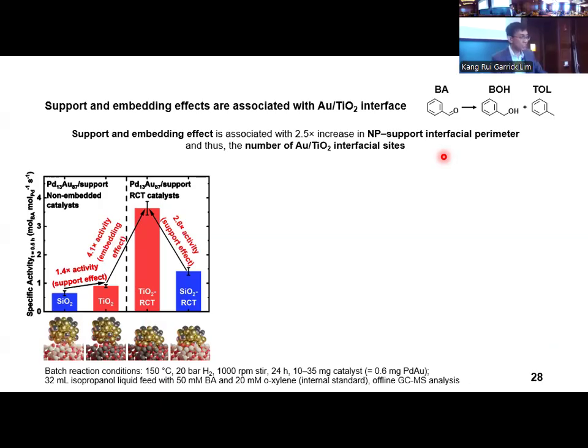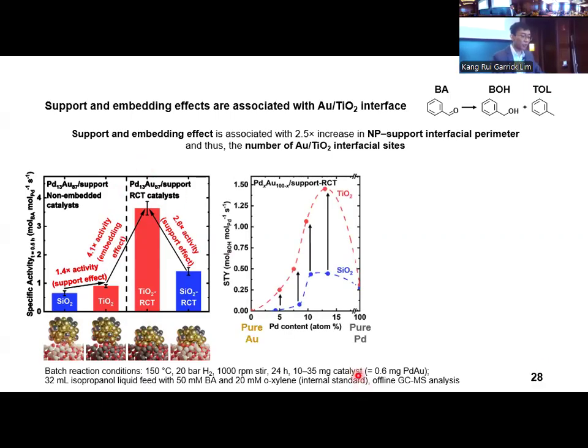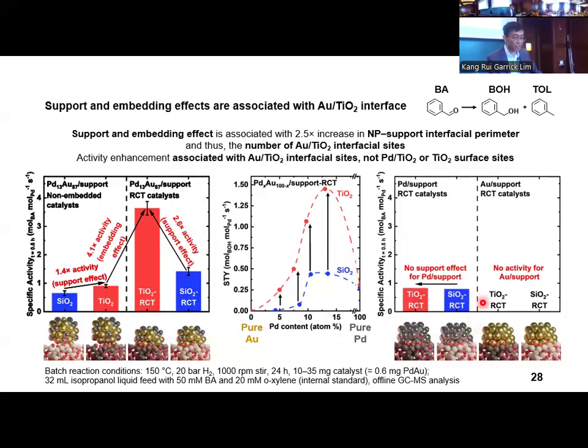Additionally, to ensure that the catalytic trends were not specific to just one nanoparticle composition, we also prepared catalysts with a range of other palladium gold nanoparticle compositions and verified that the support effect applied similarly to all other bimetallic palladium gold nanoparticle compositions we prepared, but not to the monometallic gold or the monometallic palladium catalysts. Importantly, the similar activities of the palladium catalyst confirms that the enhanced activity of the titanium-supported RCT catalysts are due to the gold titanium interfacial sites and not due to the palladium titanium interfacial sites or the titanium surface sites.